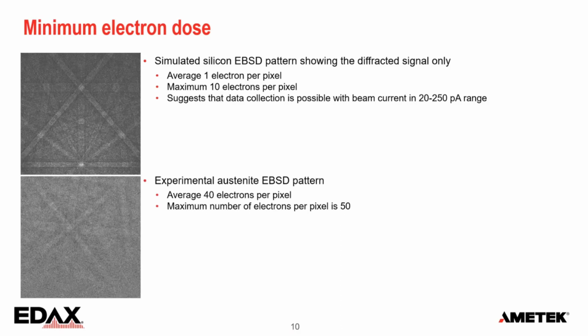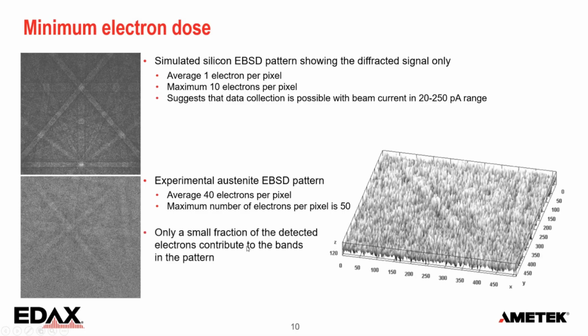But if we look at an experimental pattern, this is austenite. And here we have an average of 40 electrons per pixel. And the pattern looks a little bit worse than on the silicon one. And remember, the silicon pattern of the simulation doesn't show any background. That means that a very large fraction of the electrons that hit the sensor don't carry the information that we want. So in this case, we have on average about 40 electrons per pixel, and the maximum is only 50. So this 1 to 10 that we see in the simulation, we get in the experimental pattern as well. And that means that only 20% of the electrons that hit the sensor are showing the bands, 80% is just background noise.